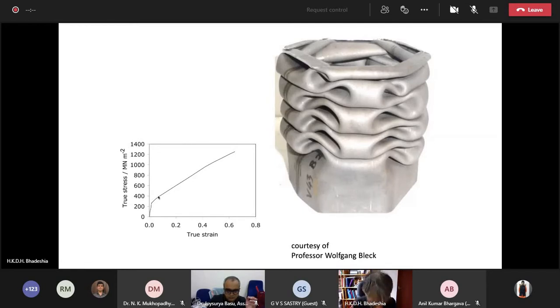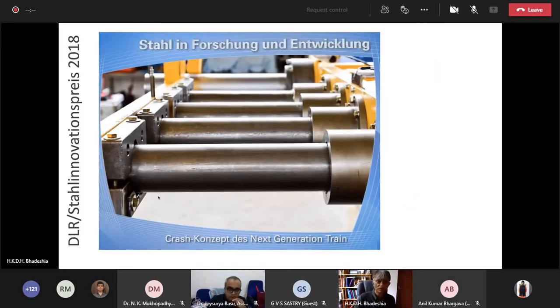So do you abandon this idea? Well, this work that I'm going to show you is done in Germany, and it's incredibly innovative. So what they did is design a method so that you get uniform deformation. Okay, so these objects here are made from TWIP steel. They are cylinders of TWIP steel, and they're designed so that in a crash they would become extruded. Okay, so that extrusion gives you uniform deformation throughout the material, and you get much better energy absorption.